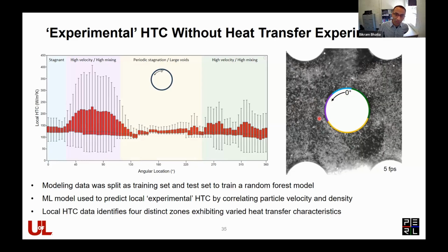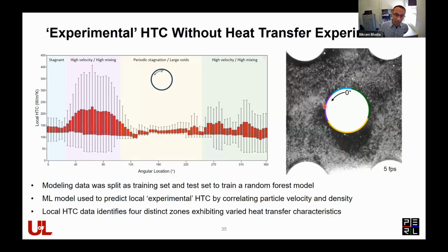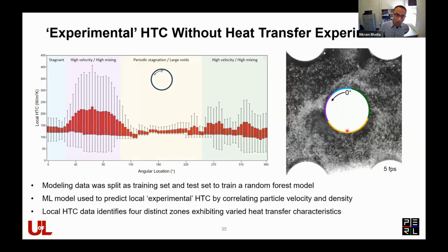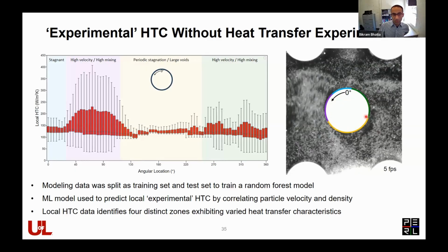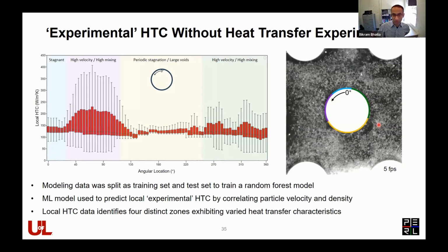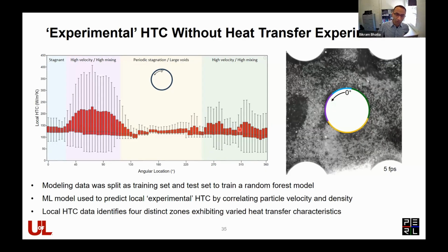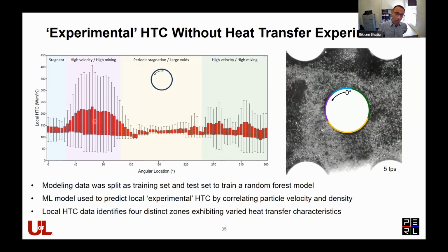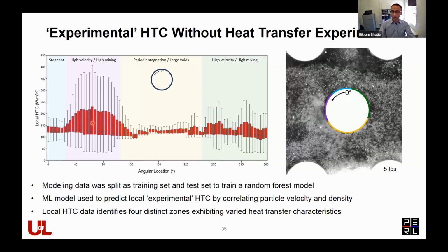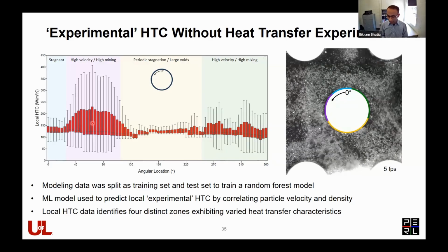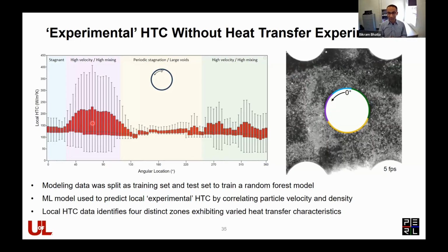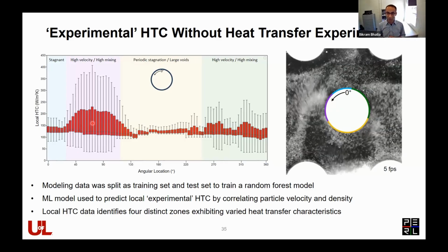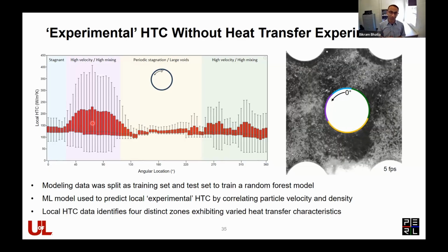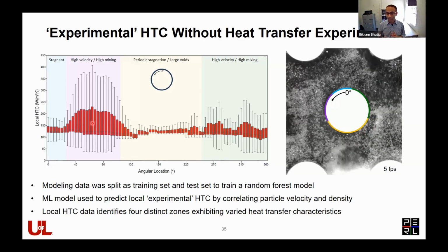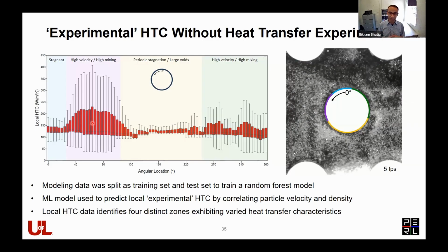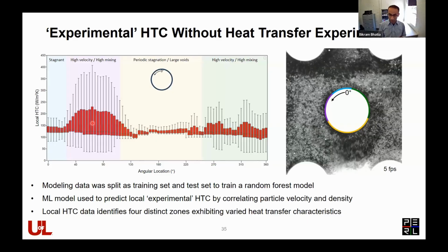And then you have this high velocity, high mixing area on the vertical edges. And on the bottom, you have a periodic stagnation and these large voids. And also you have some high velocity mixing on the other vertical wall, which gives you relatively high velocity and high heat transfer coefficient, but not as much as what you see on the left hand side. So that excited us, and we're working towards looking at more configurations and mimicking different hierarchical structures for different kinds of heat exchangers based on this approach.